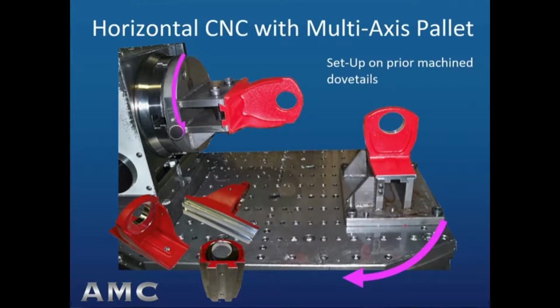The fixture at the left rotates the casting to access the face of the vertical feature and the sides of the gusset features. As machining begins, the casting on the rotating fixture has just come off the prior vertical CNC single axis setup that machined the dovetails. As you can see, the machined dovetails are now the setup feature for the completed machining in both fixtures. The casting on the right-hand fixture has come from the drilling and boring accomplished in the rotating fixture. The insets at the lower left show the finished machined casting in its 3 planes of machining.